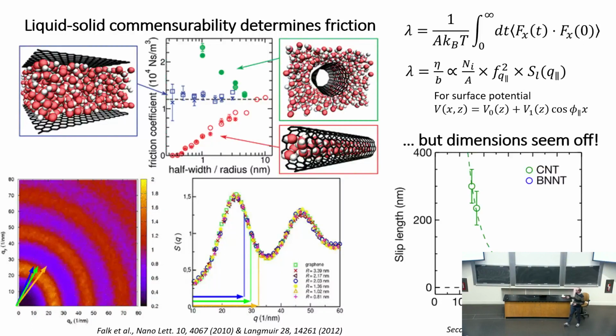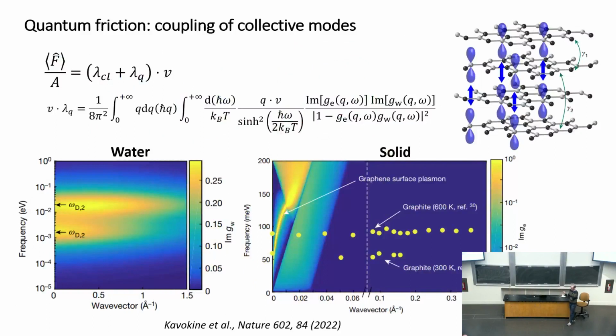However, the experiment shows that the slip length, or the inverse of the friction coefficient, scales already quite a bit at radii which are much bigger than this. So something else must be going on. And a recent development actually looks at many-body physics effects. I'm not going to go into too many details here, but it's possible for this scenario to get a closed expression. And what they suggest is that the friction force is actually composed of two components: the classical component that I just discussed, and a so-called quantum friction term.